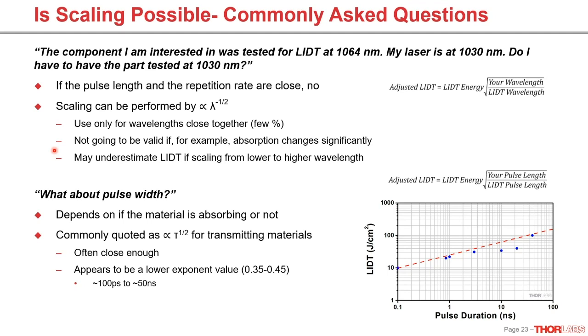As far as pulse width, this is going to depend if the material is absorbing or not. This is typically quoted as approximately proportional to the root of the pulse width for transmitting materials, and this isn't an absolute. You can find values in the literature with a lower exponent ranging from 0.35 to 0.45. And this is valid from approximately 100 picoseconds to approximately 50 nanoseconds. But as I mentioned earlier, try not to scale more than an order of magnitude. Otherwise, this can just give you a ballpark idea rather than an exact value. So that's that.